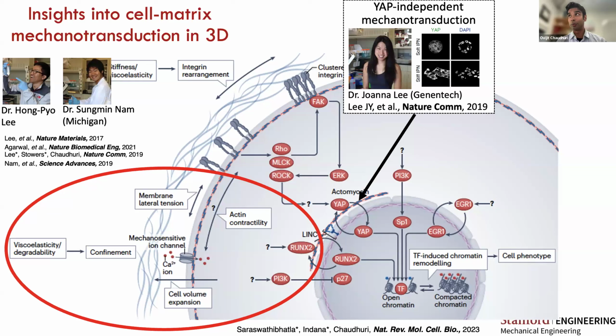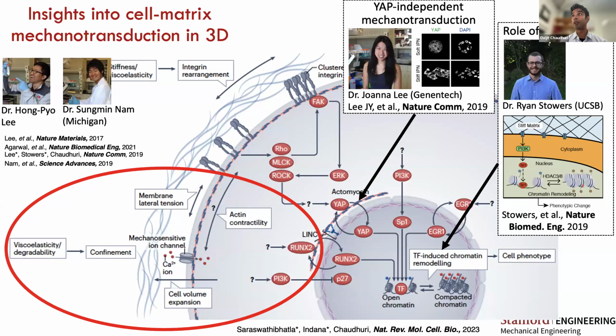Some other highlights of what we found is that mechanotransduction does occur independent of YAP in some contexts. So that's what Joanna Lee, a former postdoc in my group, found. She now has her group at Genentech. And we've also found a role of the epigenome in mediating mechanotransduction. These are studies led by Ryan Stowers, a former postdoc in my group who's now at UC Santa Barbara and has his own group. And he found that in response to changes in matrix stiffness, in this case, there are broad changes in chromatin accessibility, which functionally mediated mechanotransduction and mediated a change in phenotype.